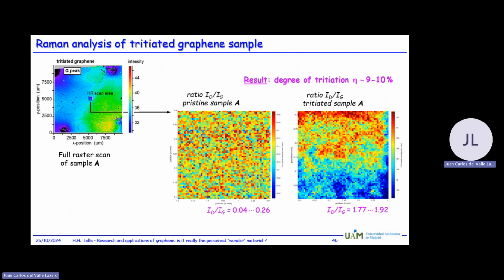That's one. And the second thing is the way we move our sample is that it is probably tilted a little bit, and we correct for this tilt. But how good that is is anybody's guess. So we then did some other experiments where we stayed at one point more or less and moved the sample less than the laser spot, simply to probe a little bit away from the center. And that then depends on the time after the hydrogenation, where you are not exactly certain how much hydrogen or tritium is absorbed or how much damage you have done to your sample, which is a very time-consuming process to evaluate. But there we are down to less than 0.1% in difference.